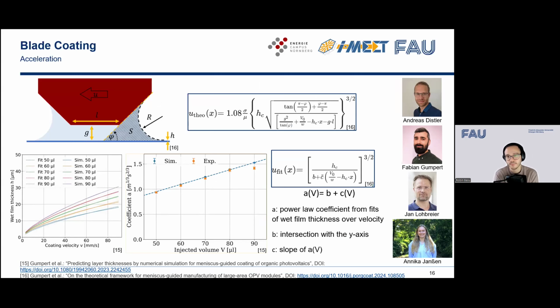This formula uses the surface energy and the dynamic viscosity as some of the main impact factors next to all of the geometries that you can see on the left-hand side. But to make things a little bit easier, they also found a fit formula that works well with the theoretical formula, that uses a power law coefficient from the fits that you get for the wet film thickness to the corresponding coating velocity.